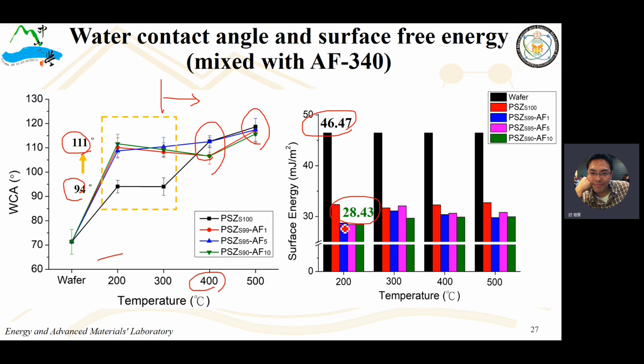I will just mention that when the surface energy is below 30 millijoule per meter square, the antibacterial effect is generated. So this is the boundary, a limit right here. If the surface energy is below 30, that means the surface can be antifouling or antibacterial.